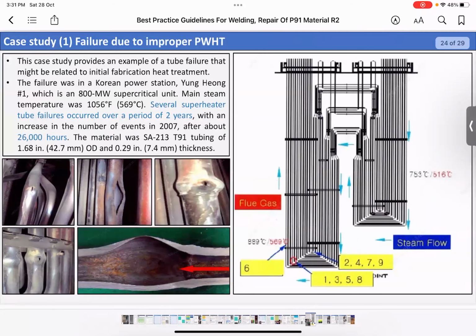The first case study is related to failure due to improper PWHT. This has happened in a superheater tube. The tube failure occurred over a period of 2 years, after 26,000 hours. The material was P91 tubing of 1.68 inch or 42.7 mm OD and 7.4 mm thickness.